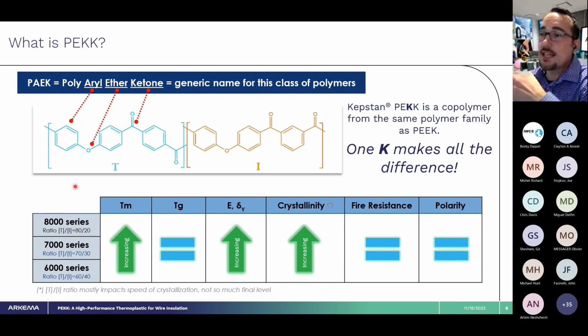Now, things that will stay the same across the grades are the glass transition temperature—there's a few degrees difference between the two, which I'll show in numbers on the next slide—and the fire resistance and flammability, because this is essentially the same molecule, same polymer. By adding another ketone, we actually have a higher polarity, but that's uniform again across the different series of PEKKs.